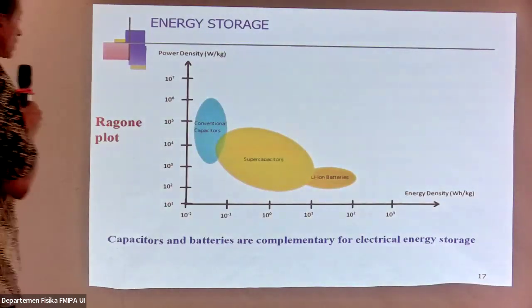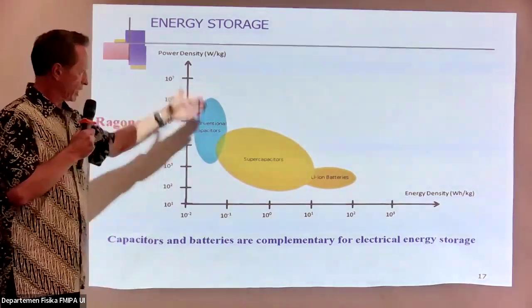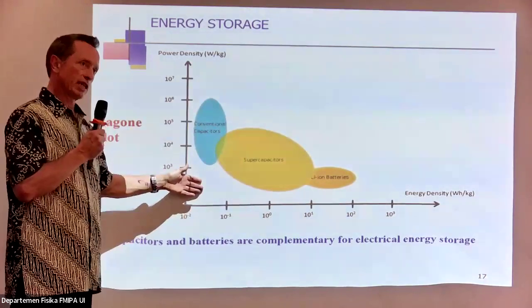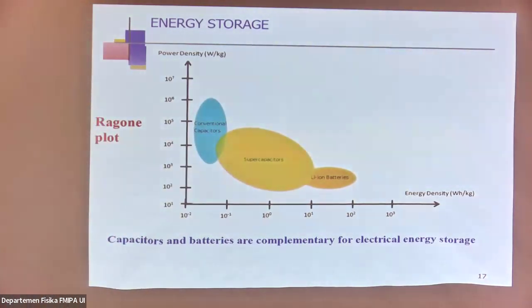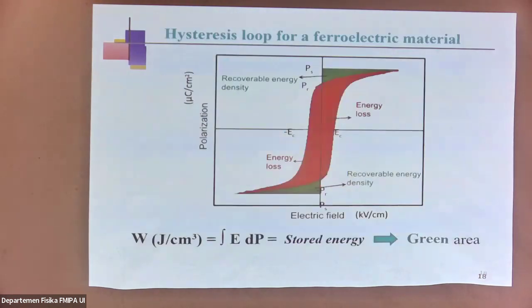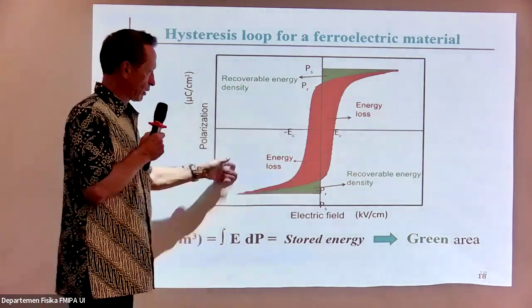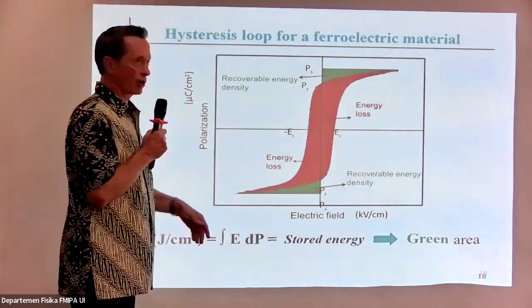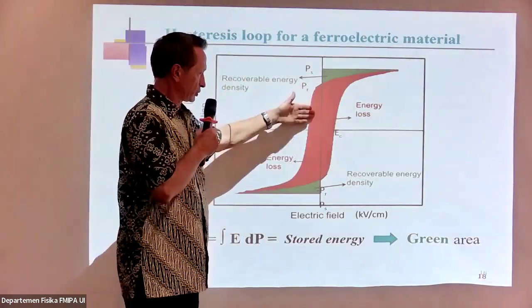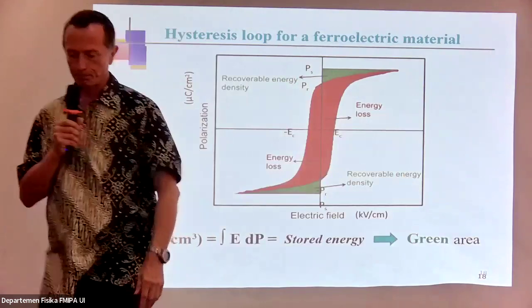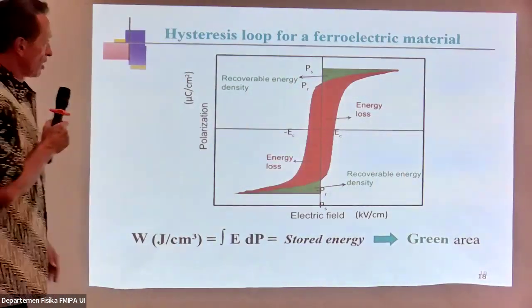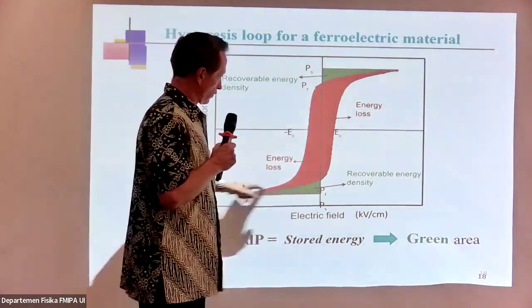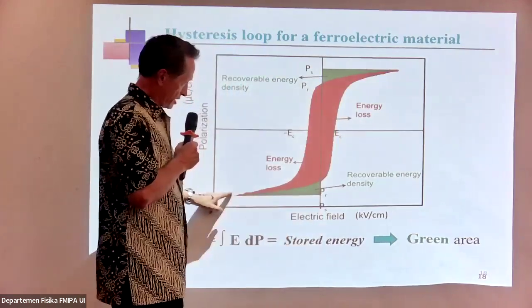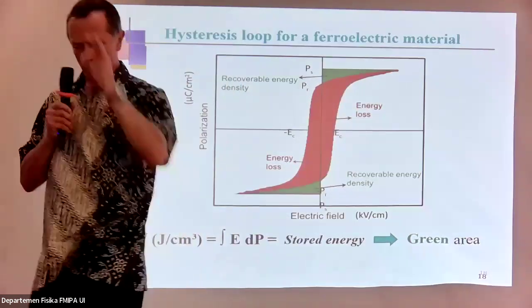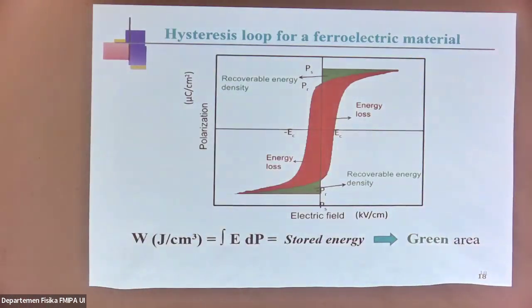So here, in my study, we're interested in high power electrostatic capacitors. And I move back to this famous and well-known cycle, the ferroelectric cycle, also called the PE loop, polarization as a function of electric field. On this figure, you have the classical ferroelectric shape in red. This is the common response of a ferroelectric material.